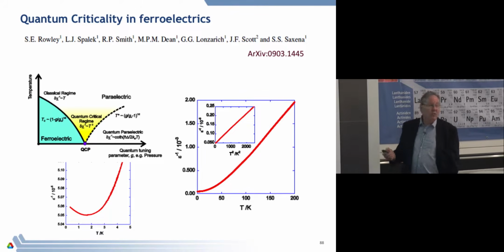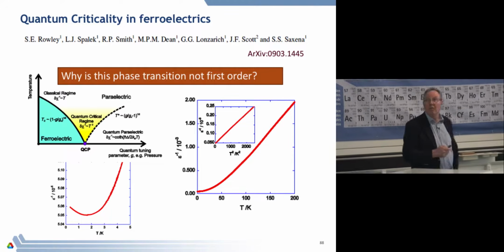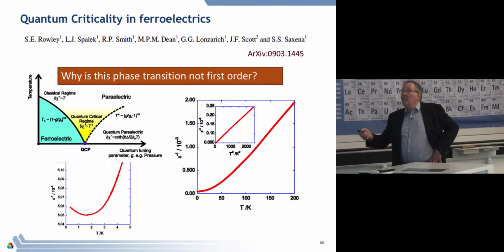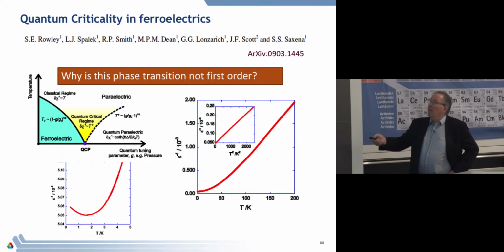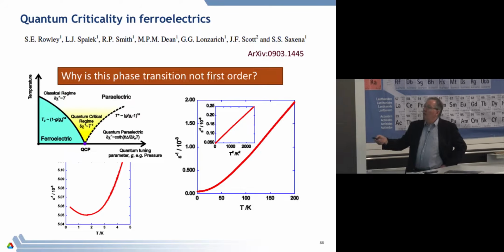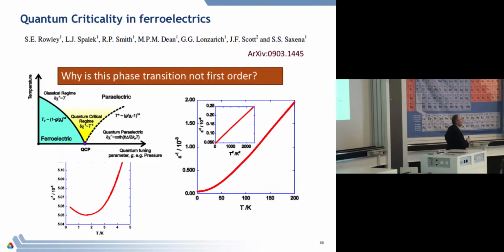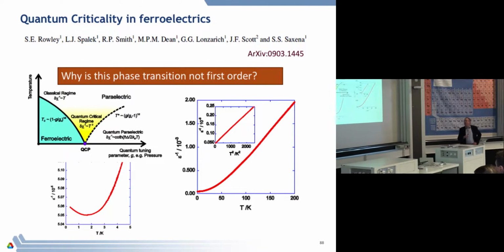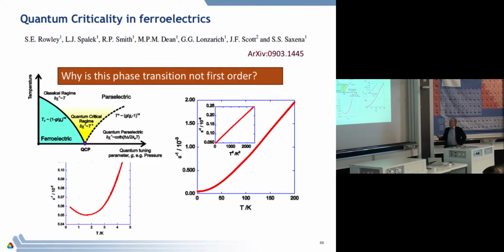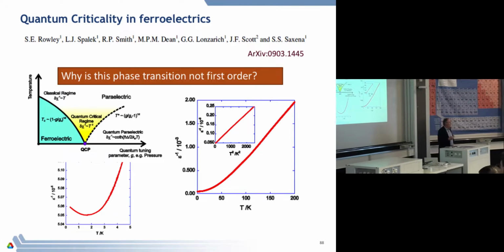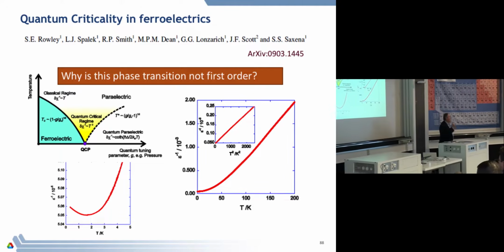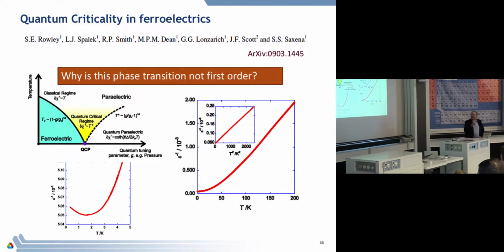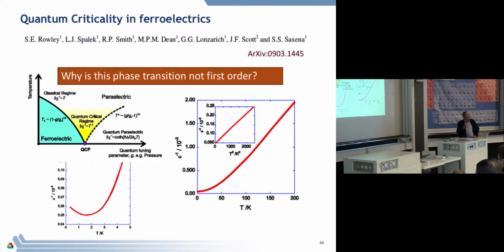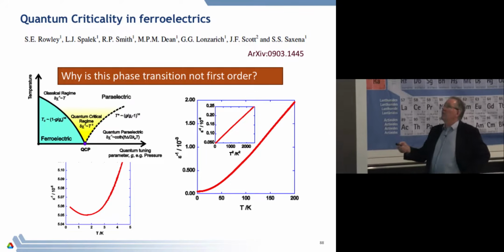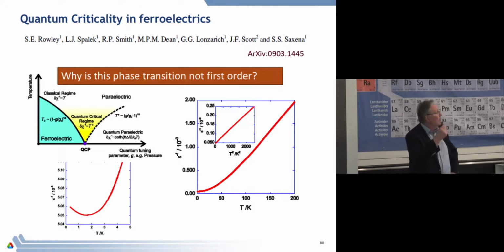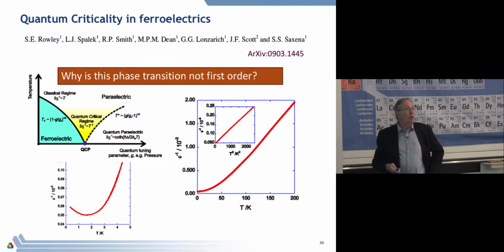And one of the puzzles, actually, about materials like strontium titanate is why this near ferroelectric behavior, well, in fact, you can drive it ferroelectric by changing from O16 to O18 or with pressure. Why is this phase transition not first order? Because all of the theory that we would have seen so far should suggest that this phase transition should be first order, because the coupling to the elastic strain should drive it that way.